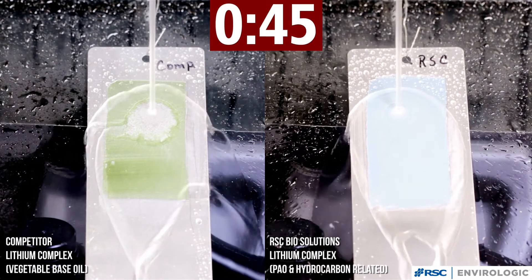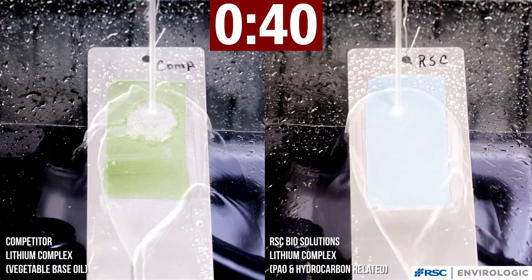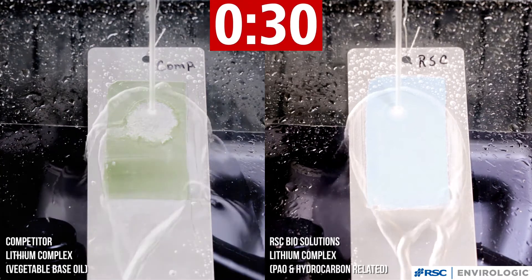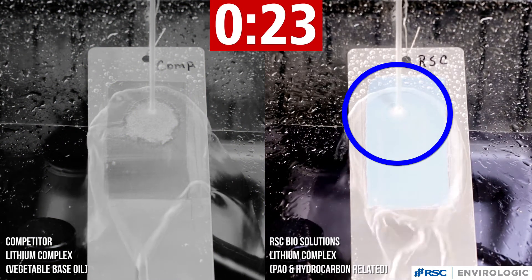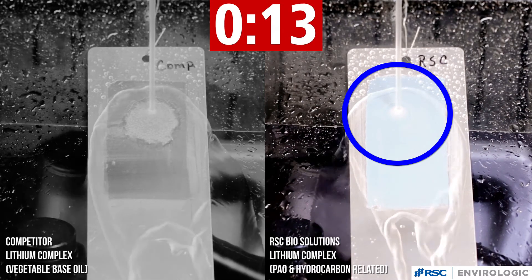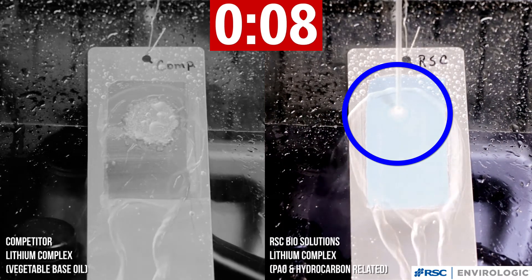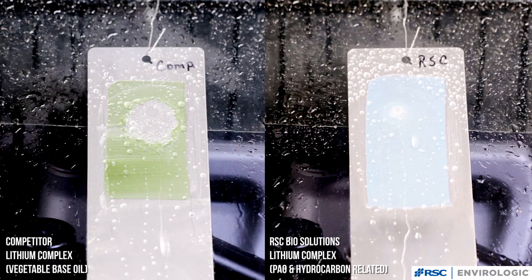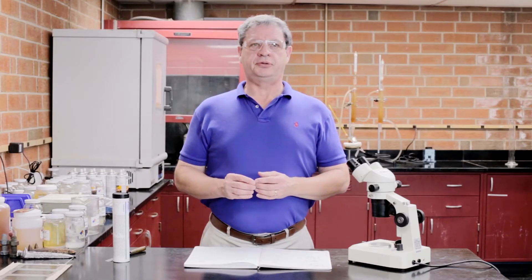Note that the film thickness of the grease on the panels is 0.01 inches or 10 mils. As you see, the RSC grease has maintained a layer of grease with a very minimal amount of grease moved out of the test area when compared to the competitor's grease that leaves very little grease on the middle surface.